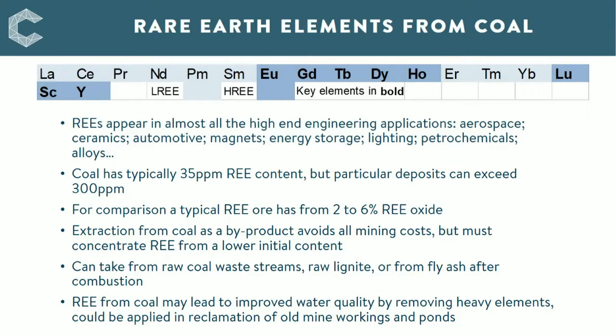The light rare earths have density less than iron, and that is a significant separation. But the heavy rare earths in the darker blue, there's a slight error on the slide, are the more valuable elements. And the additional scandium and yttrium are very expensive elements, up to $15,000 a kilo.